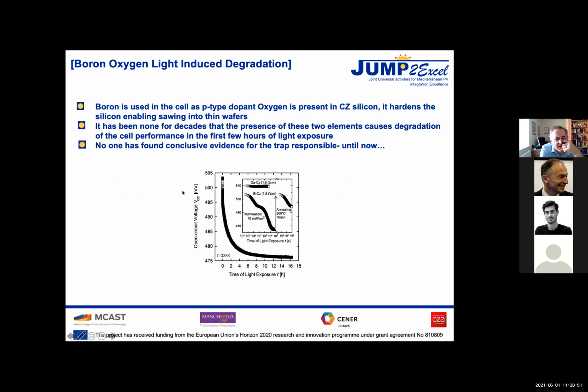So when you make your solar cell, boron is used to make the P-type material, the absorber for the solar cell in the majority of modern solar cells. Oxygen is present because it's Czochralski silicon, and it's difficult to get away from that. People have been trying to put nitrogen in instead to harden the silicon, but nitrogen also produces various defects which are a problem. So at the moment, we still have oxygen in there. It's been known for decades that if you have those two elements present, then when you turn on the light, you expose a freshly made cell to sunlight.